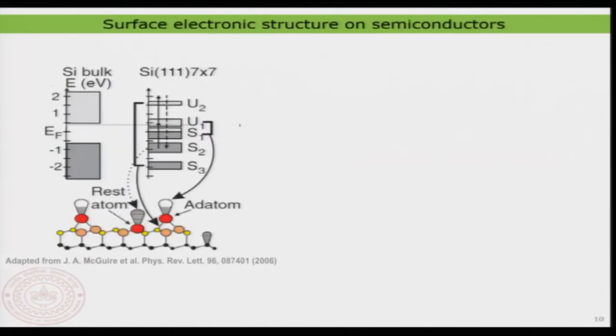That's nice. I want to show you a comparison here, using UPS and STS to understand the electronic structure of a semiconducting surface. This is something that we have already talked about. We have here the silicon bulk. The expectation is this, but the interesting thing is that silicon 111 would undergo a reconstruction, and therefore you expect something like these kinds of surface states. The S1, S2 are surface states near the valence band, and U1, U2 are surface states near the conduction band.